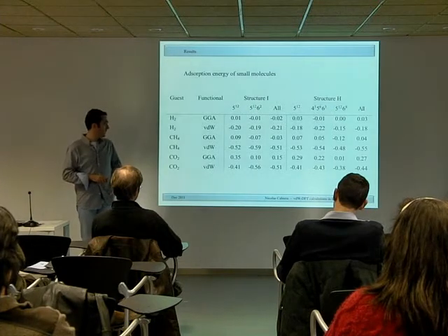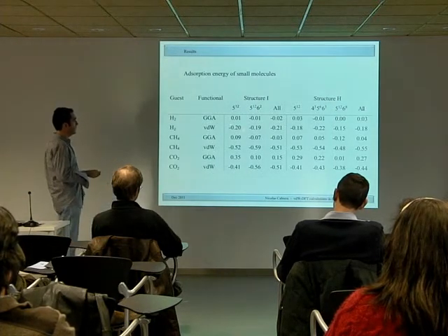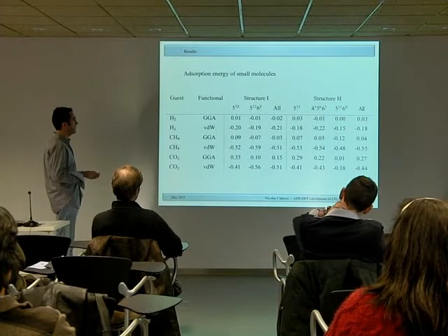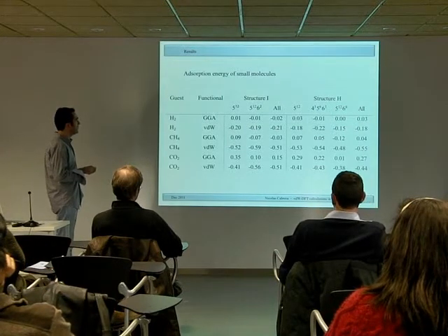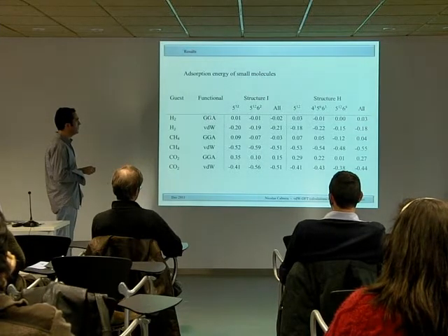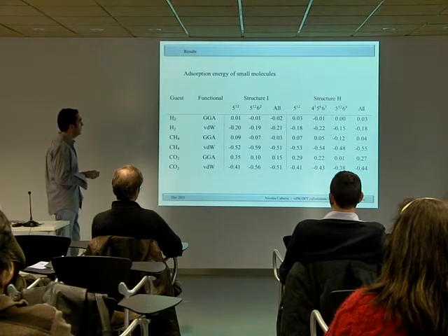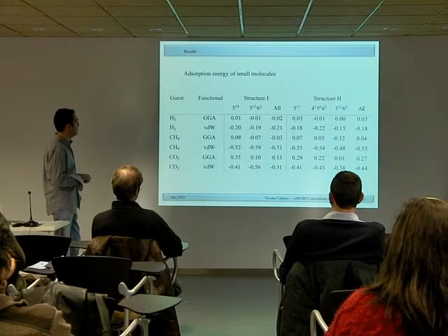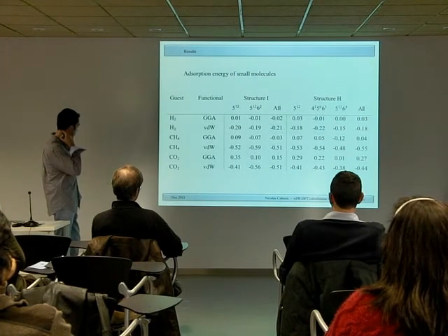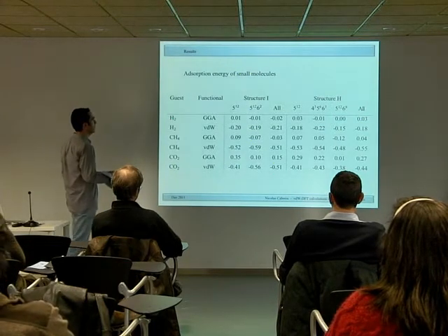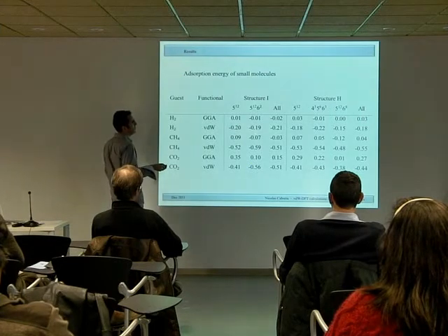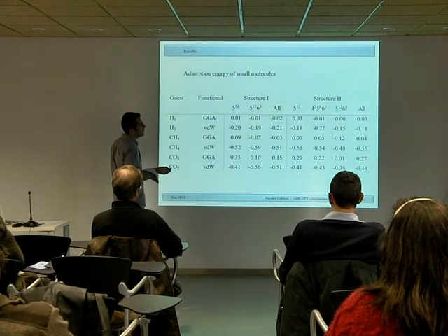The first conclusion we can read is that van der Waals governs the adsorption and stabilizes the structure. Even more, if we don't take into account van der Waals interaction and we use the generalized gradient approximation, this structure will not exist. The second conclusion we can see here is that all these numbers, the adsorption energy in different cavities, are more or less equal, except for this cavity, which is the biggest one.